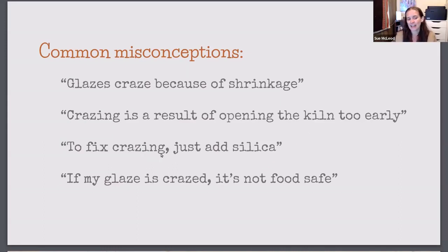A lot of people say to fix crazing, you just add silica. Now, this can work in some cases, but as we learned with the stull chart, matte and glossy, if we just keep adding silica, eventually our glaze will be underfired. If we have a matte glaze on the left side of the stull chart and we add silica to fix crazing, we might end up with a glossy glaze. So adding silica, while it can in some cases reduce thermal expansion, is definitely not a blanket solution. And there are other better ways to reduce thermal expansion aside from just adding silica, which of course I will teach you in the art of glaze chemistry.